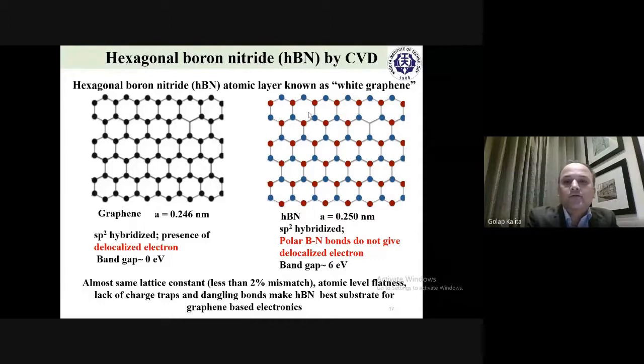So many people, although graphene has very high mobility, when you make devices you have to put it on some insulating substrate. People use silicon oxide, but in silicon oxide you have lots of dangling bonds, due to which the carrier mobility is reduced significantly. So people nowadays use HBN. HBN is insulating, with a high band gap. Because it's a 2D layer and you don't have any dangling bonds, you can have very high mobility of graphene on HBN. So it's an interesting aspect.